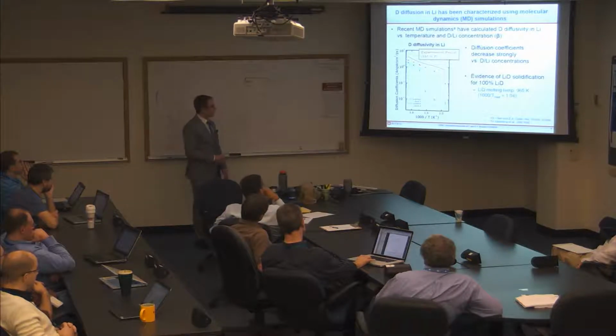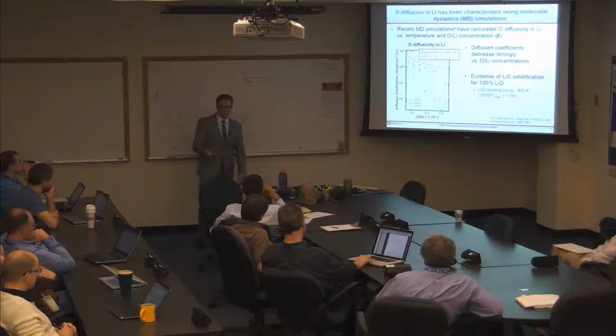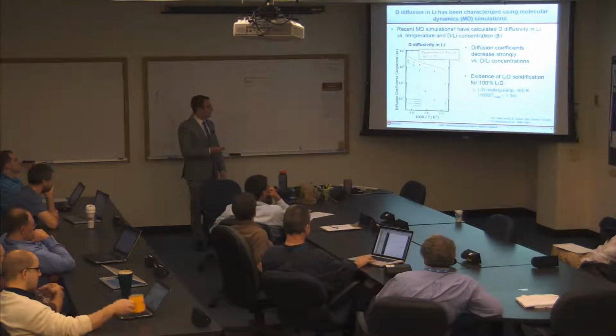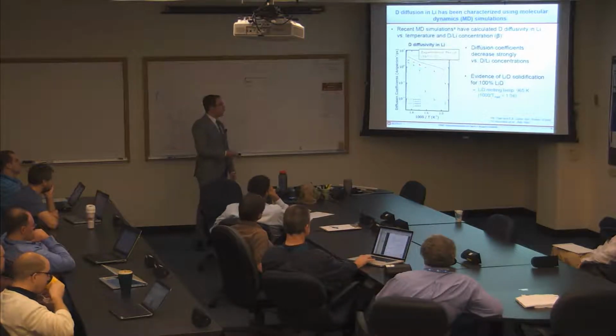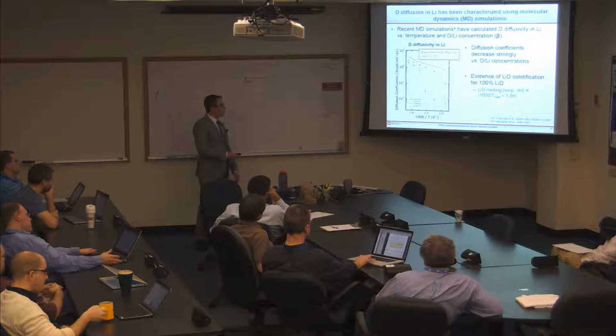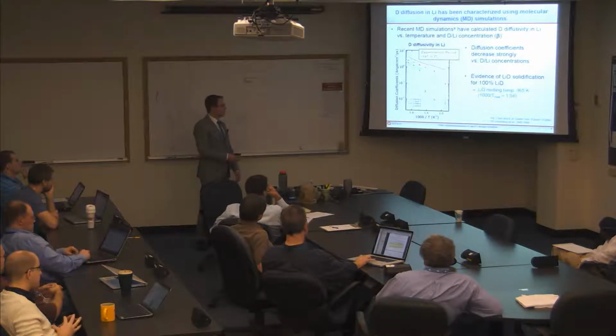And the reason that you have this discontinuity in the behavior of the diffusion rates here is due to the solidification of lithium deuteride. Lithium deuteride is a solid for much higher temperatures than pure lithium. So you expect the diffusivity not to increase until the lithium deuteride liquefies, which occurs at a temperature of about 1000 K.